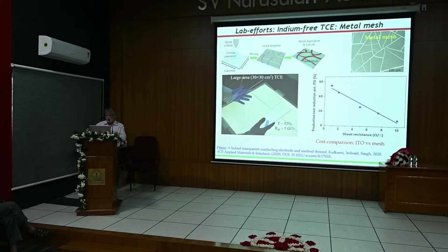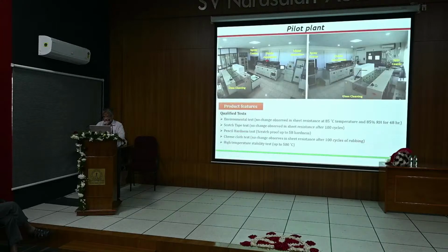A few years ago, Samsung floated a problem statement that they're interested in 0.5 ohm per square and some 93% transmittance and all. We didn't have HHV with us in those days. So we tried ourselves, but we lost because lots of these technology issues we had not addressed yet. All that I want to tell is there is global demand for such low sheet resistance coatings on glass for functional glass applications. So this is something which we achieved working with HHV.